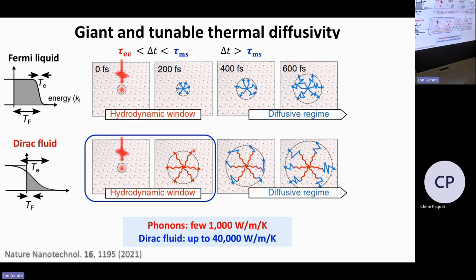Now, what is interesting about especially this part is that you actually can calculate from the thermal diffusivity a thermal conductivity. We did that, and what you get is several tens of thousands of watt per meter Kelvin. So even though before I was saying transport of heat in graphene is dominated by phonons, that's true in equilibrium, but there's a very short-lived amount of time, a few hundred femtoseconds, where if you're close enough to the Dirac point, it's actually the electron heat transport that's dominating. And it's more than an order of magnitude larger than the already record high thermal conductivity of the phonons in this system.